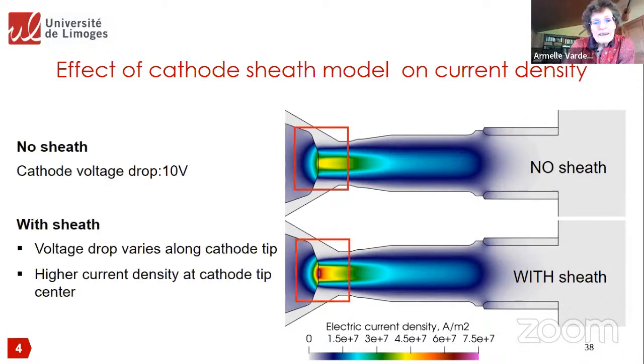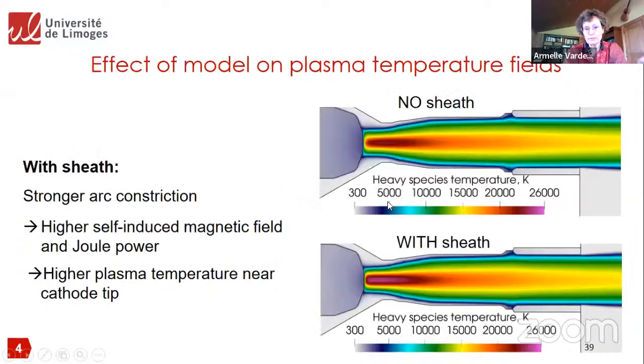And what we can see is that we have a higher current density at the cathode tip center when we have the sheath model. In addition, with this sheath model, we don't need to use some variable selected by the user, like the cathode voltage drop at the cathode, because this will be predicted by the model. So with the sheath, we have some important difference in the prediction of the current density at the cathode tip, okay?